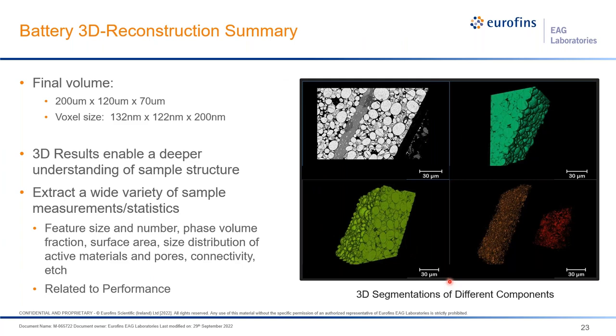So in this case, the final volume we're looking at is approximately 200 microns by 120 microns by 70 microns with a voxel size of 132 nanometers by 122 nanometers by 200 nanometers. So, you know, sub 200 nanometer spatial resolution over 200 microns, a pretty nice detailed data set. So 3D data reconstruction, and the reason you might want to do it is because it's going